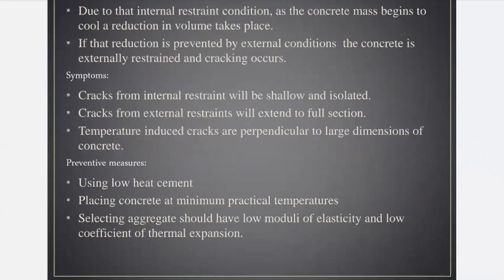The symptom for an internally restrained condition is that cracks will be shallow and isolated. Shallow and isolated means it is very small. It is not very big. It is shallow according to the width, not according to the depth. And isolated means it is a single effect. It is not having branches. It is simple. The cracks which are externally restrained will extend up to the full section, while the internal ones are only restrained up to the shallow structure, meaning width-wise.